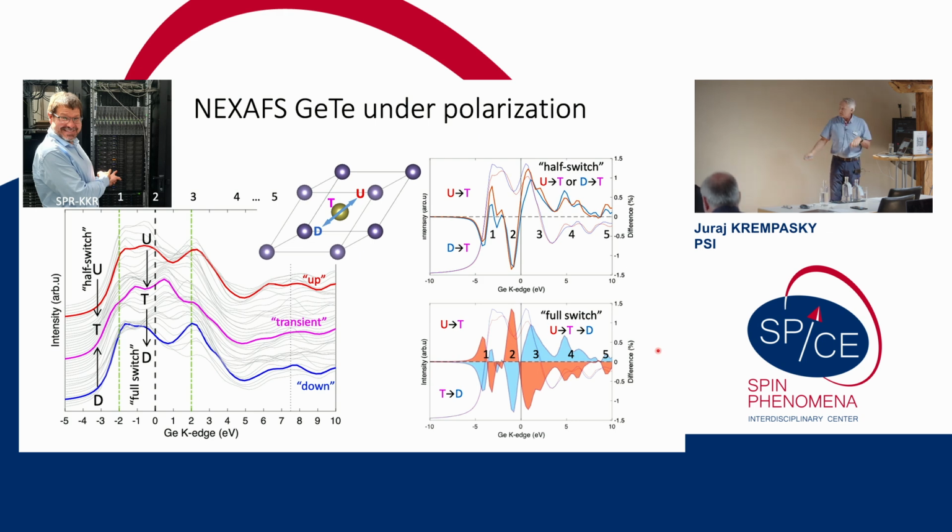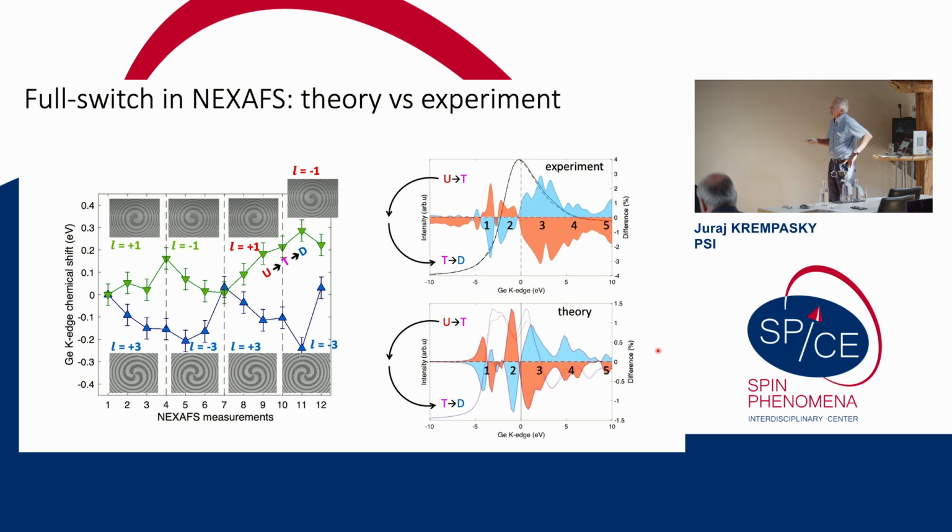Can we see exactly this scenario in our experiment? The answer is, of course. It happened exactly during this transition, +1, -1. These are the NEXAFS data from the experiment, and this is theory. All 5 peaks nicely reproduced and flipped. This is a full switch.